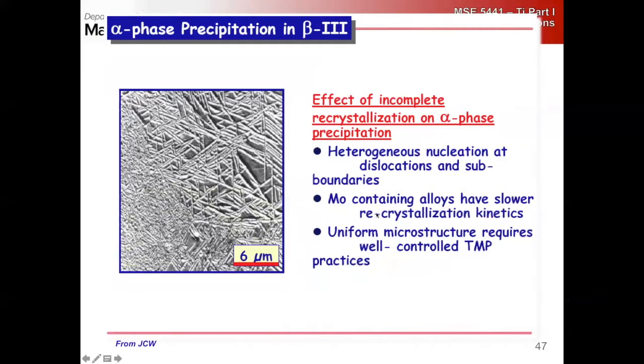And so that means essentially we're just like in steels with thermomechanical processing. Or no, we didn't talk about any processing like that in aluminum. But in the steels with the controlled rolling or thermomechanical processing, we want to maintain the recrystallization kinetics in the beta phase. We want lots of dislocations. So that means we need to slow down our recrystallization kinetics a little bit. If we recrystallize too quickly, we're going to recover a nice clean grain structure, either during the deformation or after. Metadynamic recrystallization, it's called, where you get the nuclei of the new grains, but then they grow on the aging treatment.